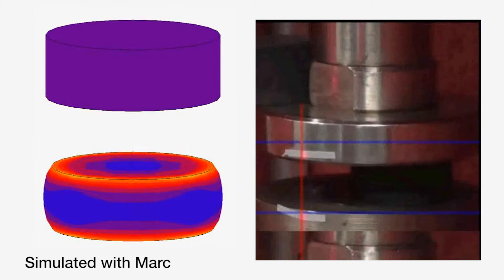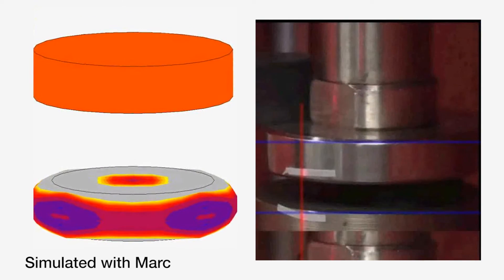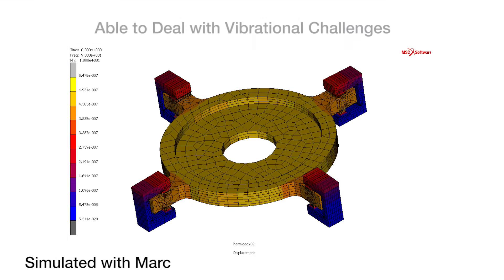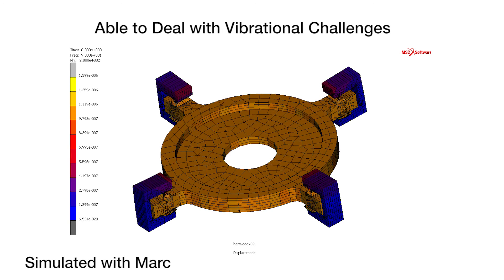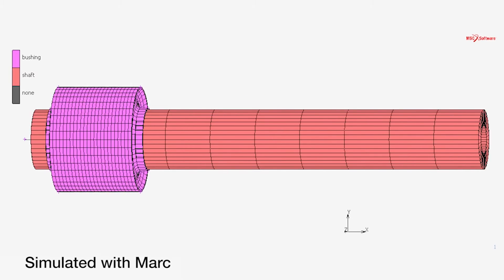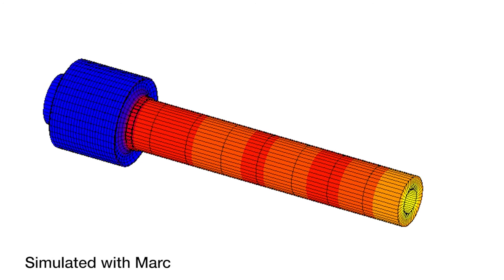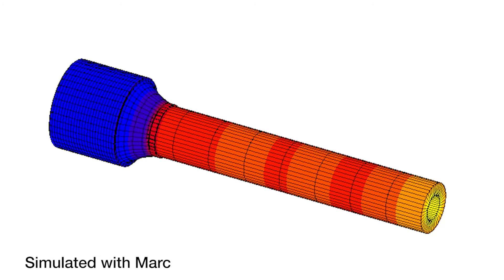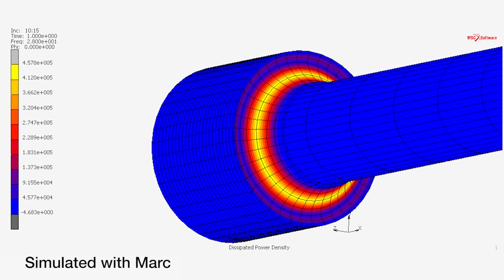They've also dealt with one of the more difficult challenges in that it deals with vibrational challenges. When we have an engine mount or a vibrational seal, the stiffness of the elastomer actually depends on the amplitude of the vibration. Traditionally these kinds of problems have only been able to be sensitive to frequency, not so much amplitude or mean strain.